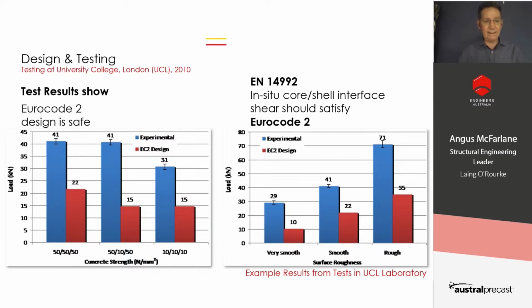The left-hand side here is concrete at various strengths. The 50-50-50 is 50 MPa concrete in the shell, the core, the shell. The 50-10-50 is 50 in the shell, 10 in the core, and 50 in the shell again. And then we've got the various roughnesses. That's the roughness on the inside of the concrete shell.